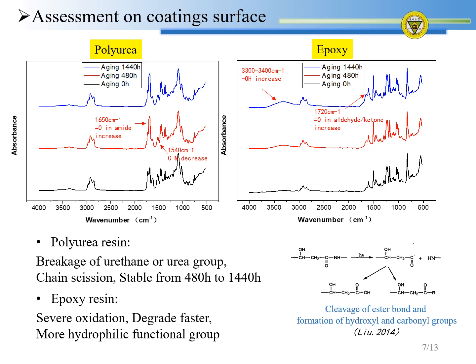But when it comes to epoxy resin, the changes are severe. The most clear is the increased peak of hydroxyl and carbonyl in saturated aldehyde or ketone. This indicates the oxidation of epoxy resin, and these are all hydrophilic functional groups. So we can explain why the water contact angle decreases.